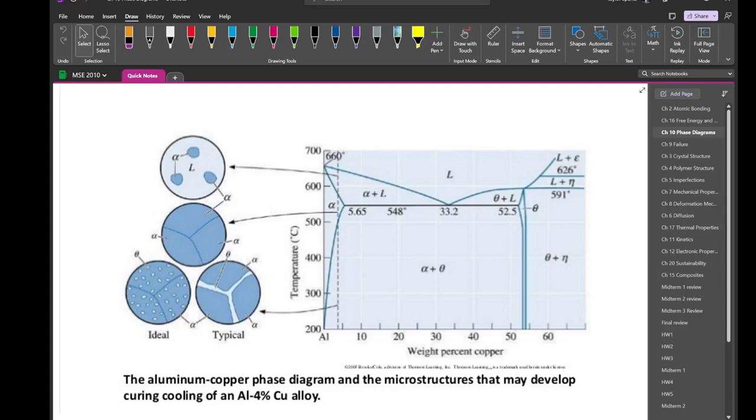And so you can get two different types of microstructures. If you did it really slowly and you held it as close to this line as you could, technically below it, then the phase is going to show up on the grain boundaries. That's where the theta shows up. If you do it a little bit faster, it's probably going to precipitate within the grains. This gives you better strength because as your material tries to deform, these precipitates are essentially hindering it. More on that later this semester. But that's an example of how you sketch it, crossing through a retrograde solubility limit.